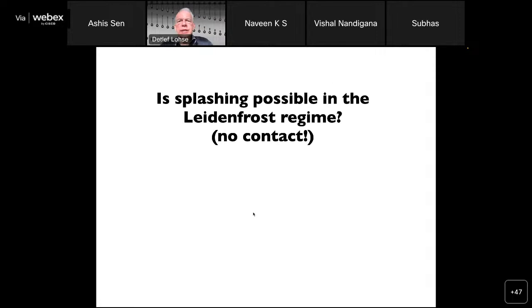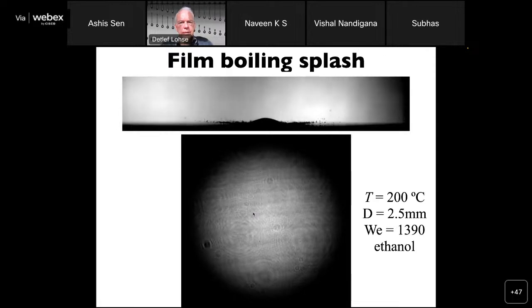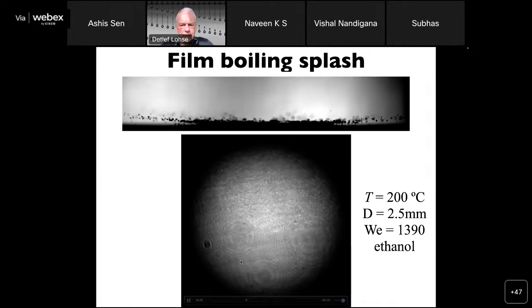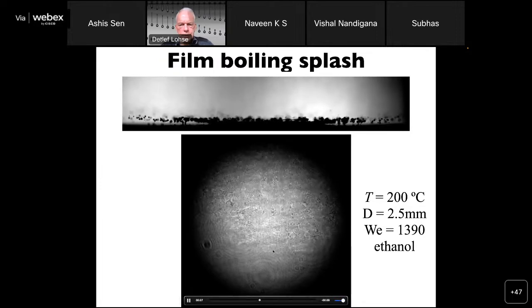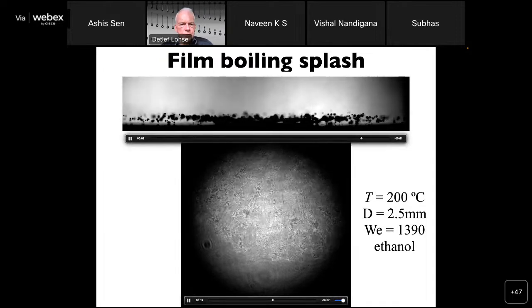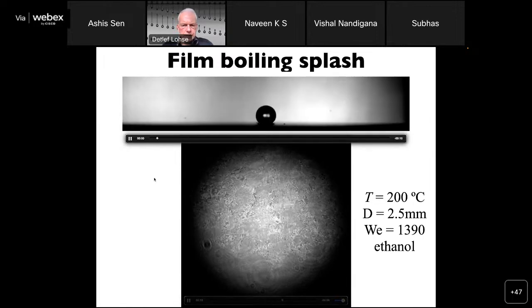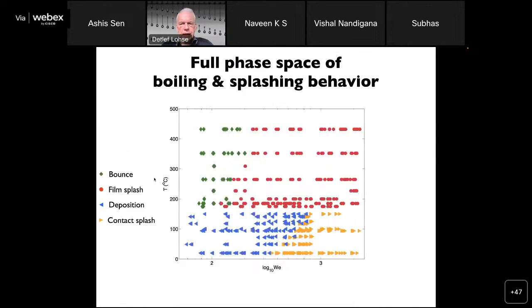The question now is, is splashing also possible for this Leidenfrost droplet without any contacts? And indeed it is. So here we see the film boiling regime. This is the bottom view. So there's really no contact, but we do see splashing. And the reason for this is that the gas in between the droplet and the substrate is flowing outwards, and then it takes liquid along.